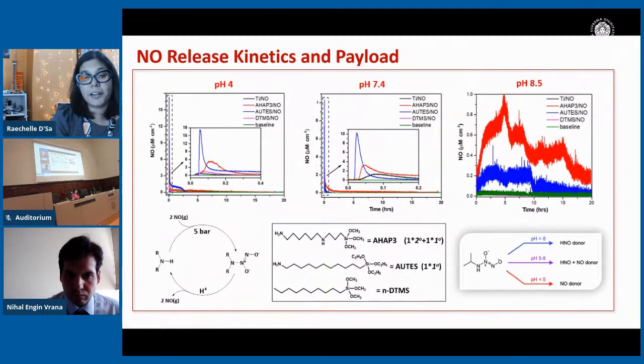One more thing to consider, which complicates the situation a little bit more, is that for secondary diazeniumdiolates, you always get 2 moles of nitric oxide release. But in the case of primary diazeniumdiolates, the amount of nitric oxide release is actually based on the pH. At acidic pHs, you get all nitric oxide. At pHs between 5 and 8, you actually get a mixture of HNO and NO, and at high pHs, you get just HNO. So this is why people mostly use secondary diazeniumdiolates,